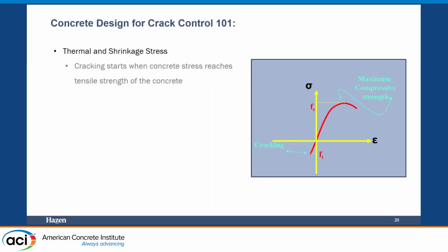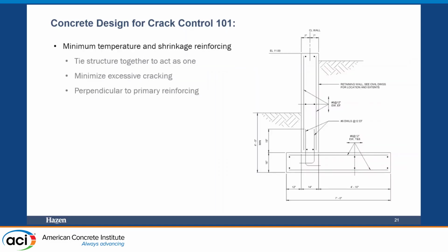Your compressive strength is much greater than the tensile strength. Tensile strength is only about 10 to 15% of the compressive strength, and cracking starts when you reach that tensile strength of concrete. Unless you gain enough strength concrete-wise to where your reinforcing can be effective, then you're going to see the cracks develop. So we want minimum temperature and shrinkage reinforcing to tie the structure together. That's 318's goal for providing minimum temperature and shrinkage reinforcing. For environmental structures, we also want to minimize the excess cracking that can occur. That temperature and shrinkage reinforcing is perpendicular to the primary reinforcement.